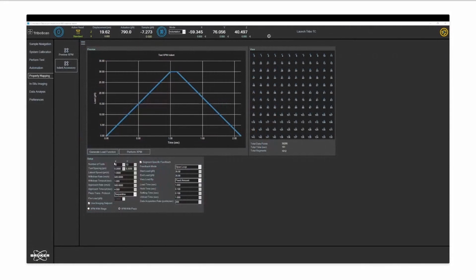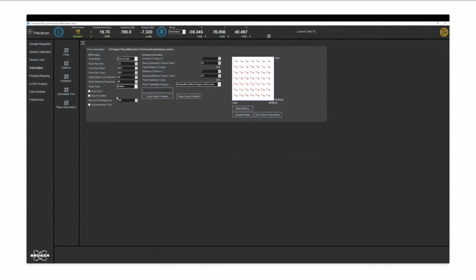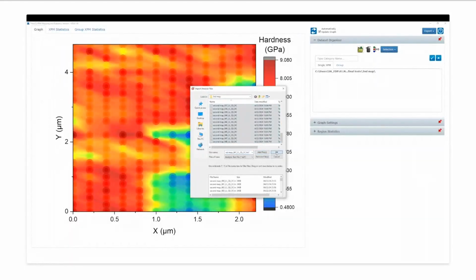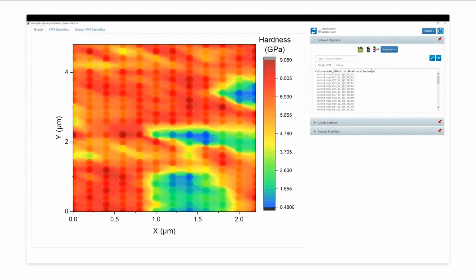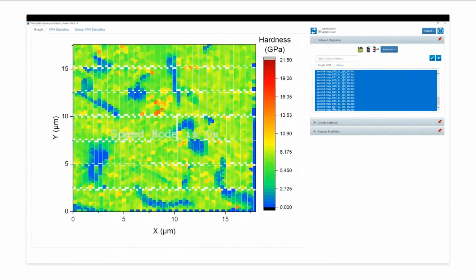Now, here is a single XPM test with a 12 by 12 grid covering about 2.4 micrometer square area. We can use this test and stitch it into a larger area using piezo automation, allowing us to make larger maps. This is a 7 by 7 grid with 2.6 micrometer spacing of that XPM test, covering around 20 by 20 micrometer square area. Now we can import all of that data into our XPM app here and see what the larger maps look like.